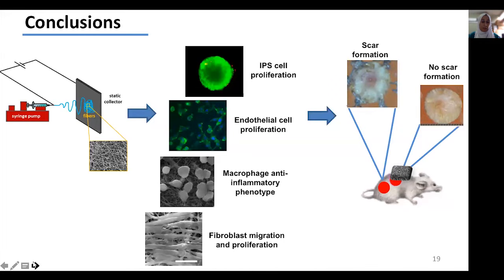To conclude, we successfully fabricated blend nanofibers consisting of seaweed-derived polymers, and we showed that these blend nanofibers could promote fibroblast migration and proliferation. They promoted macrophage polarization towards the M2 phenotype and also promoted endothelial cell proliferation, as well as supported the growth and proliferation of induced pluripotent stem cells. And most importantly, in vivo wound healing studies showed that there was no scar formation, and the blend fibers accelerated the wound healing process in contrast to the negative control or to the remaining positive samples.